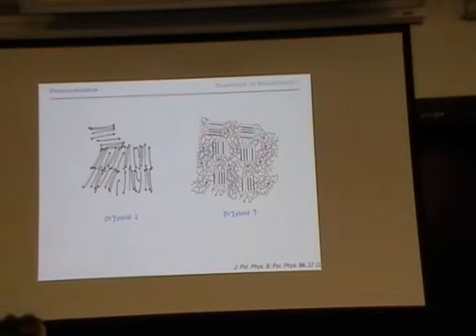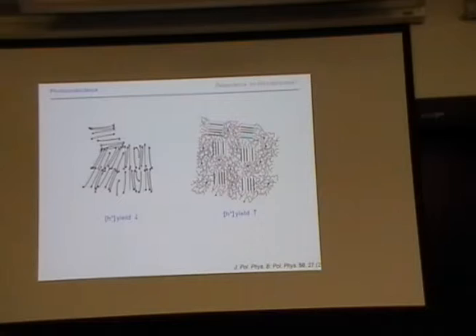So why is that? Here I have a better schematic of the small molecular weight materials. They form chain-extended crystals. However, as I said, the molecular order within these crystals seems not to be very good, as also supported by our UV-Vis experiments. The reason being these end groups really start to distort the chains. And if you have polydispersity — here polydispersity is killing because the small molecules may get into the crystals but will really distort them.